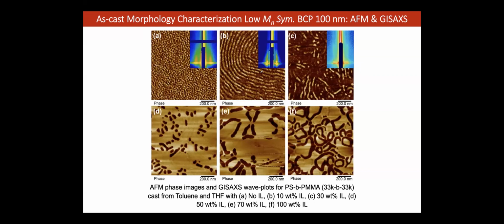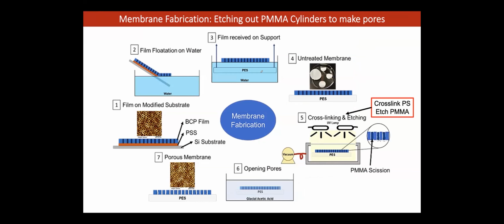So we have a ternary system, and these binary interactions act in a way so that the PMMA strong attraction to silicon is cut down by ionic liquid, which it imbibes, and thereby it makes it perpendicular because it matches the polystyrene silicon interaction. But we need to work more on this, maybe with some theorists as well. Okay, so from here on, I'll just show you a splattering of other interesting opportunities for membranes that opens up with this technique, but each of them would need a good study with GISAXS, for example. And so I'll just go through a couple of examples.